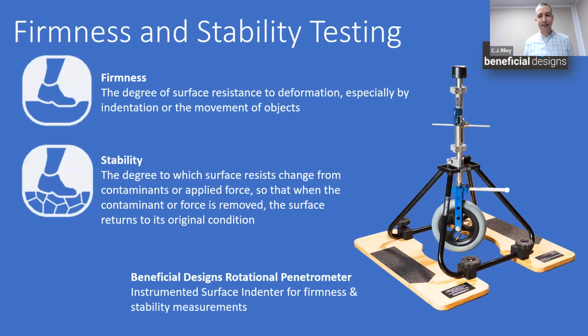All right, the first thing we did, consistent with the prior studies and really as a way of measuring what we had planned to measure, was to look at firmness and stability. And this is based on an ASTM standard and a device called a rotational penetrometer that's produced by Beneficial Designs. The firmness measurement requires the user to stand on the sides of this device and then release the wheel into the ground where a prescribed force is applied and the resistance is measured in terms of the deformation. So how far does that wheel then penetrate into the surface when released straight? The stability measurement then takes the wheel and rotates it a number of times until the measurement stabilizes and you look at the additional indentation. So both of these are displacement measures, and the lower they are, the more firm and stable the surface.